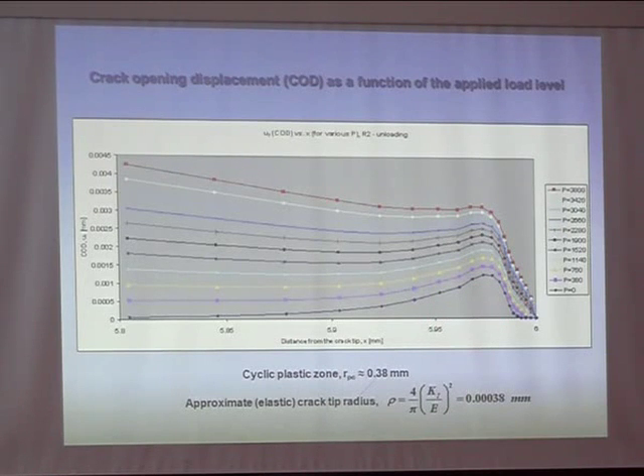at least numerically, is opening behind the crack tip. It's a hole, and that was staying always. I couldn't get rid of it. There was a contact here, and there is a contact between these elements here, but I don't know whether this is real or it's coming from this huge rotation when I'm using the small deformation theory. Now, when I calculated the pressure here, or the nodal forces, they were pretty small. So I'm not sure whether it's a real closure or not, but let's look here.